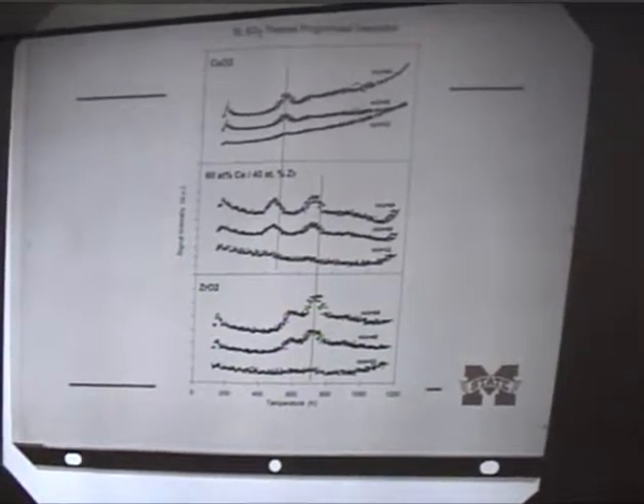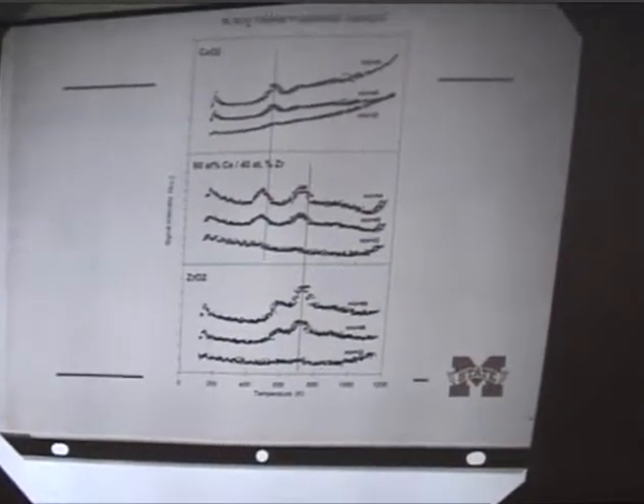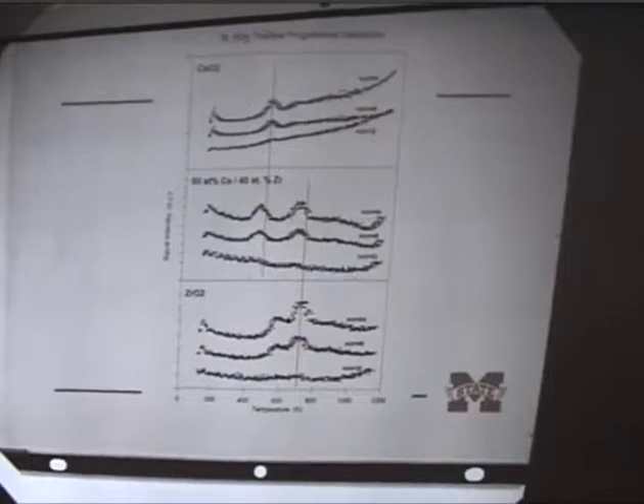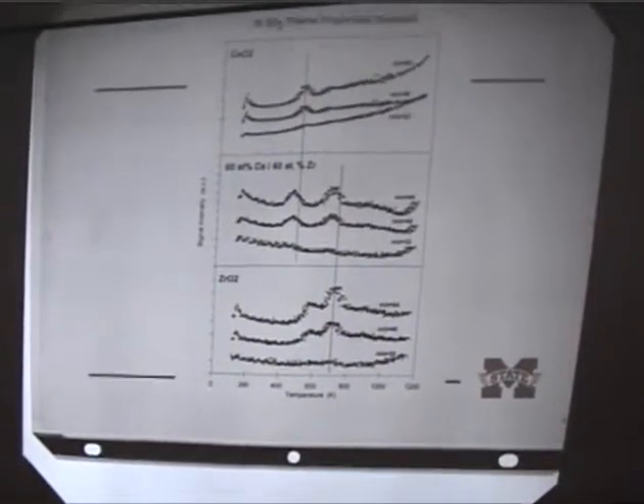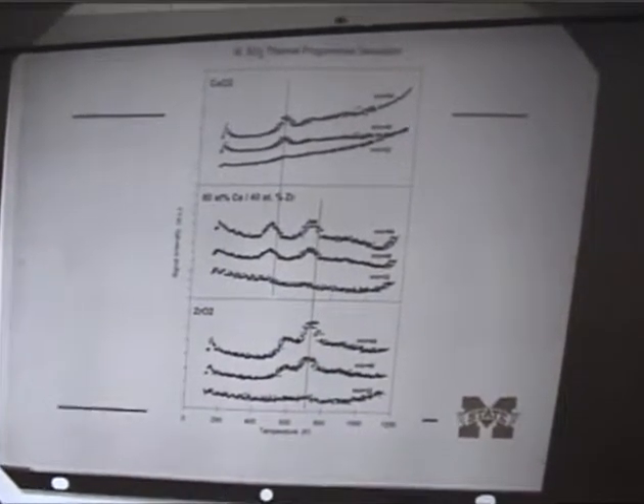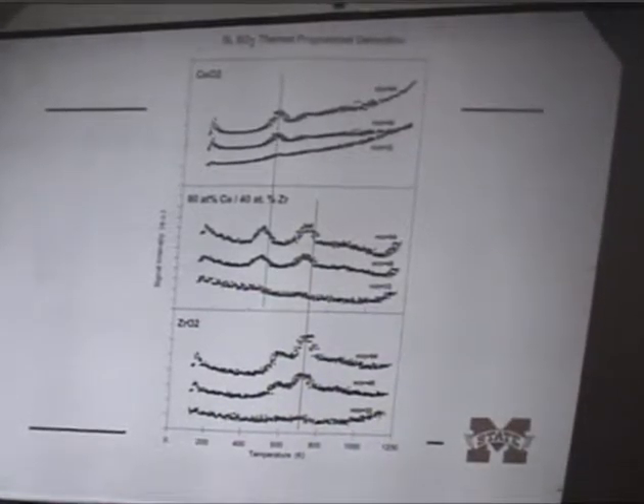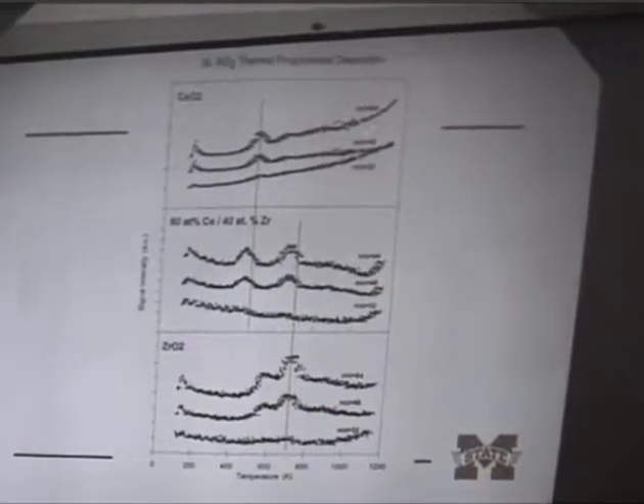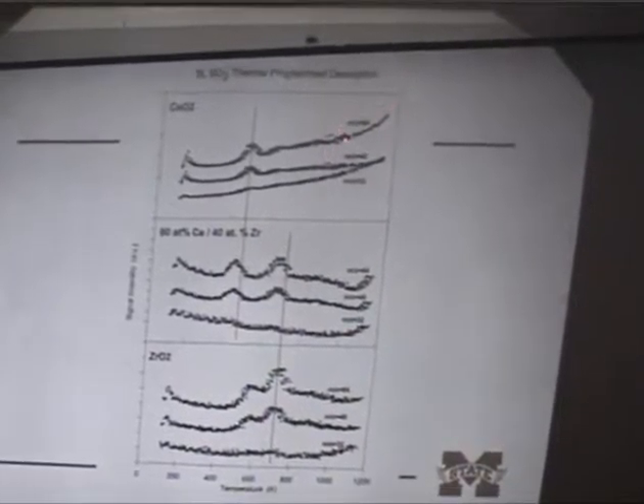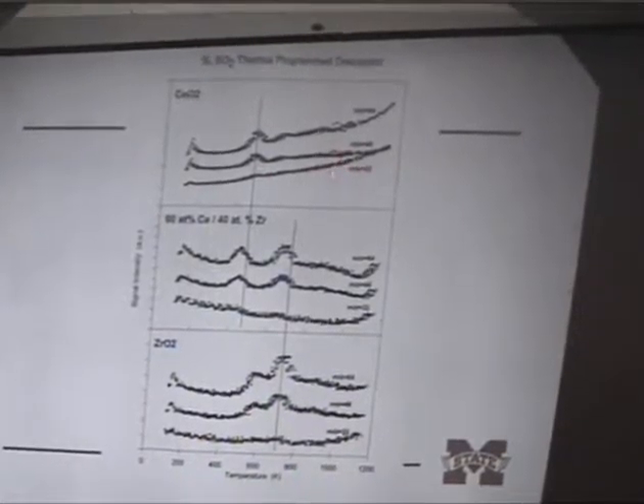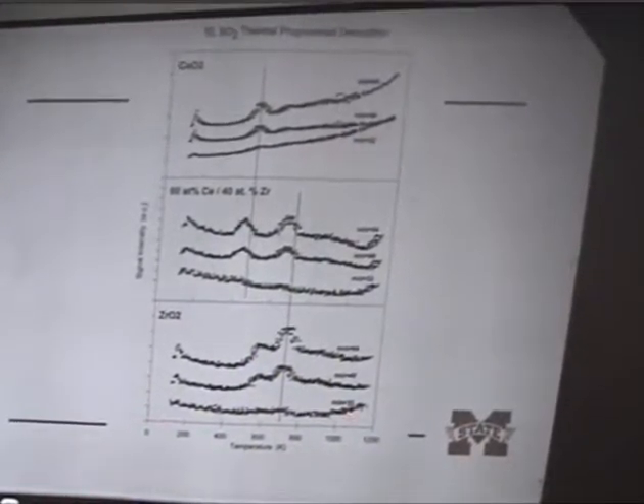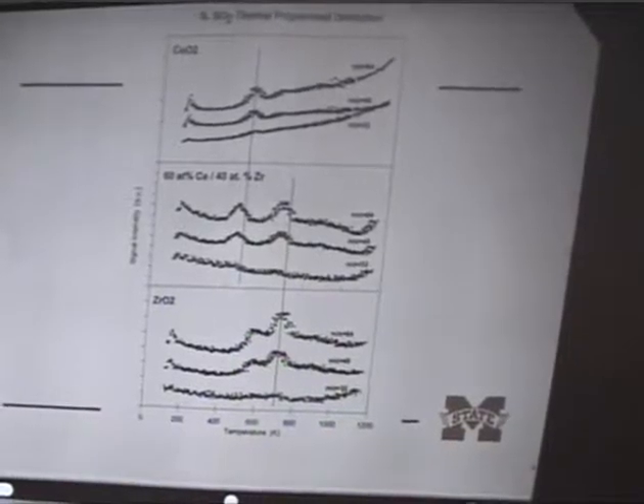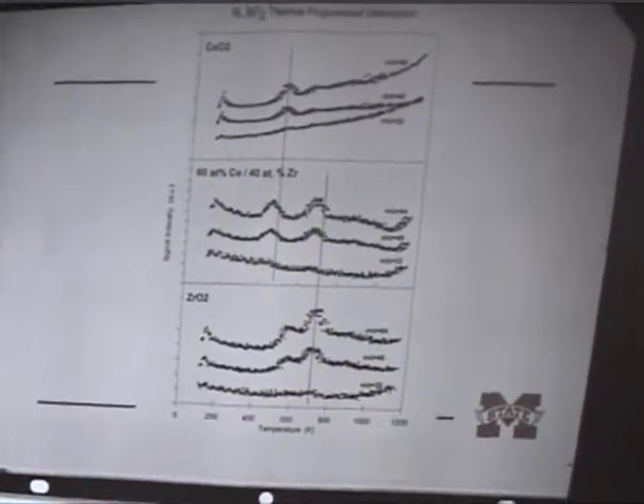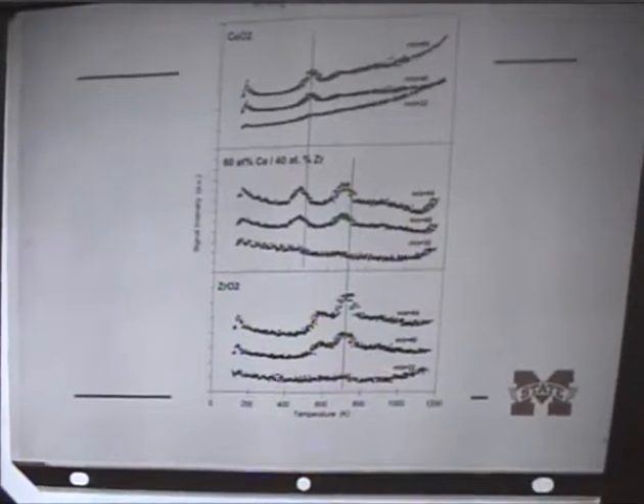In general, the only thing we saw coming off was SO2. Okay, we did not see any evidence for SO3. We're not able to detect an O2 desorption signal. And so what's shown here are the mass-to-charge ratios that we would expect for SO2, its cracking fragments, and then the one on the bottom here is for oxygen, and you can see that in essence those are flat. If you squint for water, pretend you saw something there, but in general these are flat.